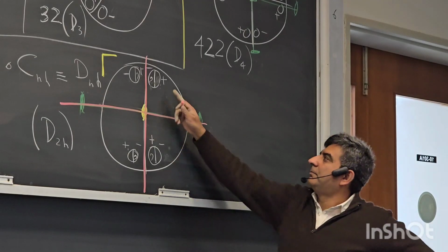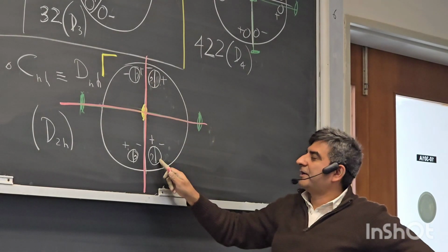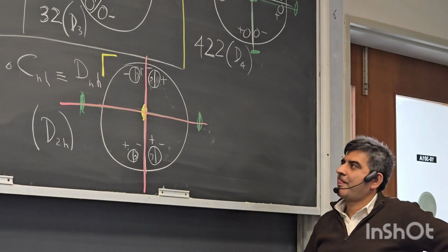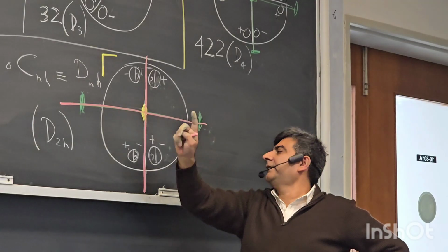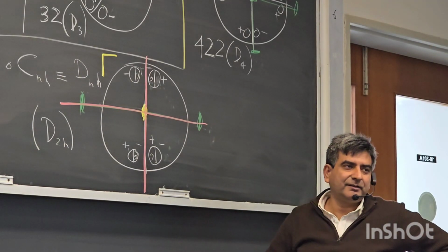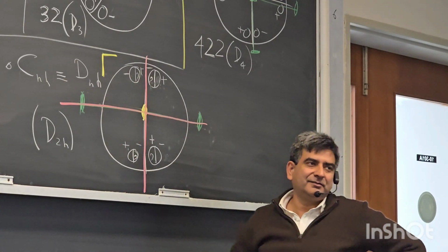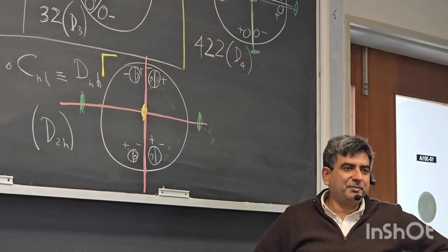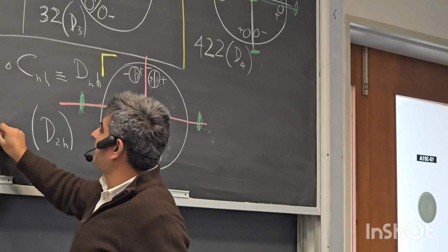It is. Plus with a comma, comma here negative, without comma negative. So this is also a mirror plane. You could put a comma here, it doesn't matter. Same thing. Is there yet another mirror plane? Yes, there was an original mirror plane as well. So now there are three mutually intersecting orthogonal mirror planes. So the international notation for this point group is mmm.